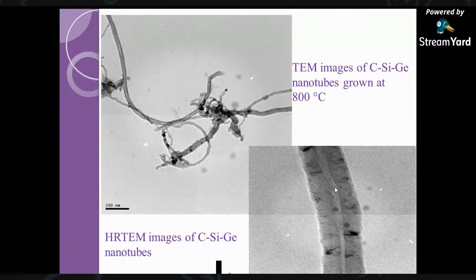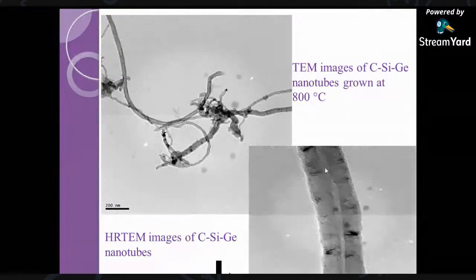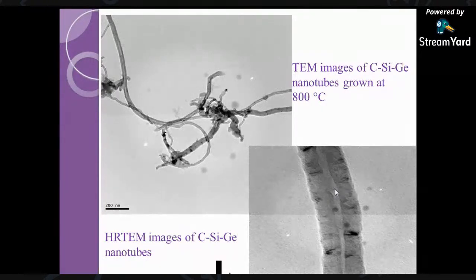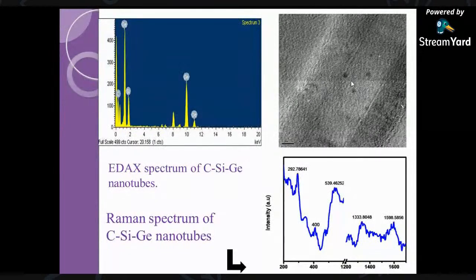We don't have tube formation in nano silicon materials. So this is a good achievement that we can take credit for, because of the incorporation of silicon, germanium, and carbon. You can find three elements in one tube. So this is the beauty of this material. To confirm the presence of these materials, we can see carbon, germanium, and silicon in the EDX spectrum. It clearly indicates that it has three components. And then you have the Raman spectrum confirming the presence of carbon, silicon, and germanium due to their vibrations.